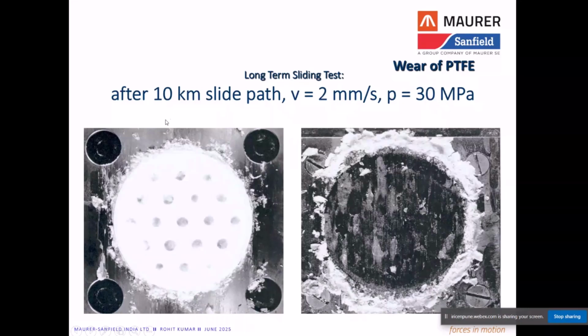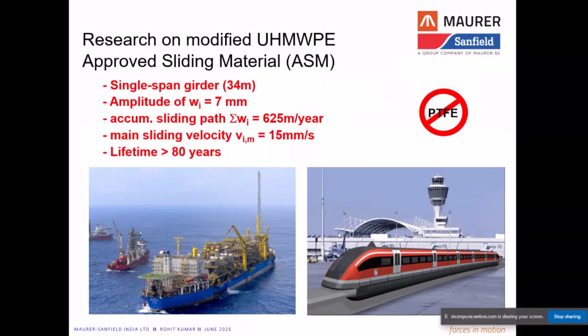During this test, considering a 10 kilometer sliding path with a velocity of 2 millimeters per second and a pressure of 30 megapascals, major failures were found in the PTFE sheet. So they found that in this situation a failure occurs in the bearings and the bearing needs to be changed. In addition to that, there are also requirements for high speeds where this PTFE has not worked. And also our requirement is for the structure to work for a minimum of 80 years.